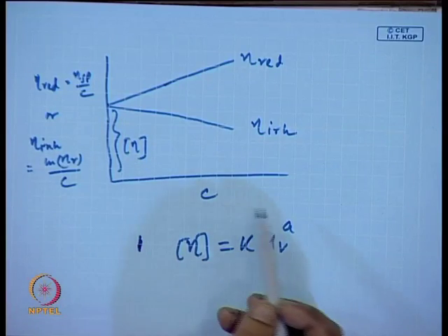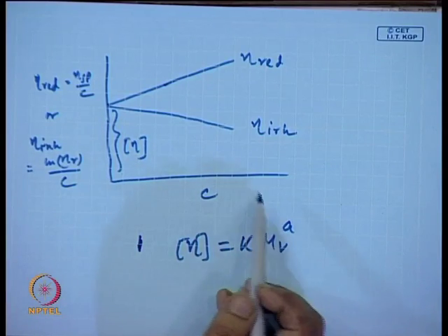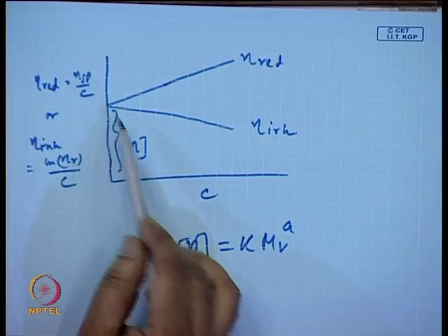So, if you measure the efflux time of the solution and the solvent, from the ratio you can get the relative viscosity, and from that the reduced viscosity and inherent viscosity. So, you make solutions of different concentration and plot, and you get the intrinsic viscosity.